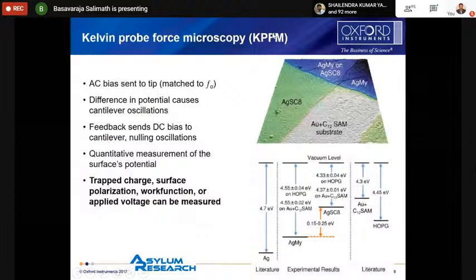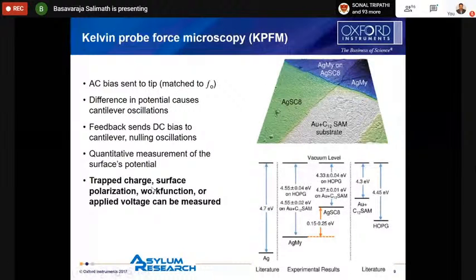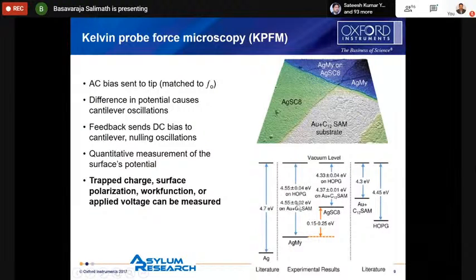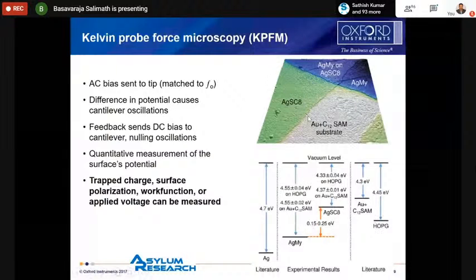And in the case of Kelvin probe force microscopy, we can find out the work function or surface polarization or surface potential of the sample. Like for example, you can see here, this is some silver, gold, some silver, different types of metals are there. So we can find out the work function of this material. So like 4.55 is for this one. That is the work function of this material. Like that, we can find out the surface potential or work function of the sample with the KPFM.